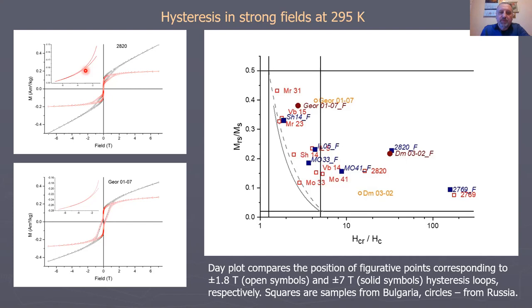And of course, just comparing the points on the Day plot from seven Tesla loops and from 1.8 Tesla loops, we can see that for the same specimen, they could plot in quite different parts of the diagram. About the only thing in common is that we have a relatively high MRS over MS ratio and relatively high Hcr over Hc ratio, as we should expect from a mixture of soft and hard phases.